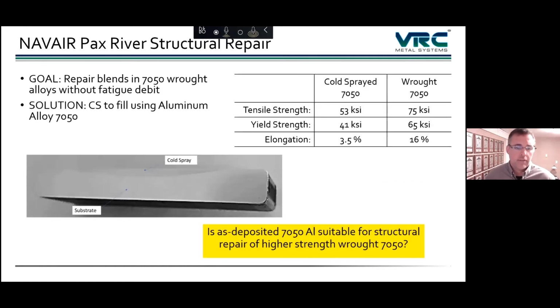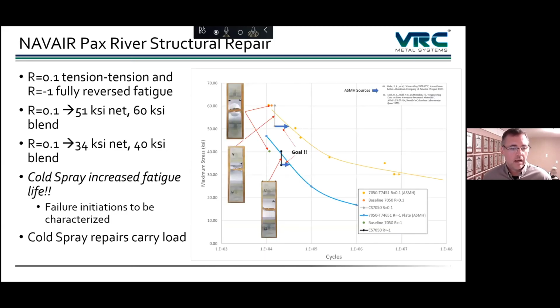Now, in this case, we have a cold sprayed 7050 material. This is a much higher strength material. The base material is much higher strength. It's a wrought material. So in this case, our cold sprayed material is not quite as strong as the wrought material. However, in the same type of test, we still see an improvement in the mechanical properties. We're not getting an order of magnitude improvement, and we're not necessarily getting up to the strength capability of baseline material without a divot, but we are seeing an improvement in the properties.